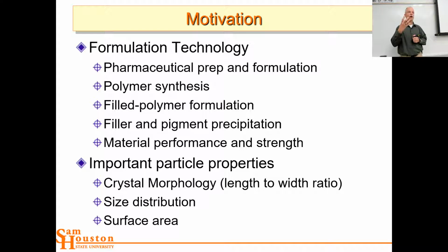So if you have a really large, bulky particle that's going to dissolve slowly versus microparticles that dissolve fast, if you want a fast-acting drug, you want the smallest particle size possible so that you have a lot of surface area and you have a fast dissolution. If you want a time release, you want a large chunk of molecule and you want it to be coated. Maybe you want to preserve that coating until it gets into the small intestine where that drug's going to be more bioavailable. So notice how we've never changed the chemical identity of the active ingredient. We've just changed the physical properties. So tuning those physical properties could be really important.